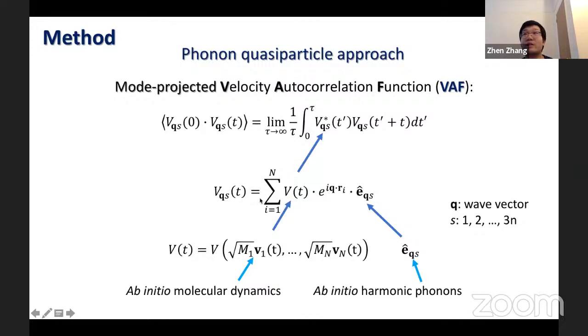It can be calculated from the atomic velocities obtained from ab initio molecular dynamics simulations and the phonon polarization vectors obtained from harmonic phonon calculations. So M here is the atomic mass, and capital N is the total number of atoms in the supercell in the MD simulation. Q labels the phonon wave vector, and the S indexes the 3n phonon branches of an n-atom primitive cell.